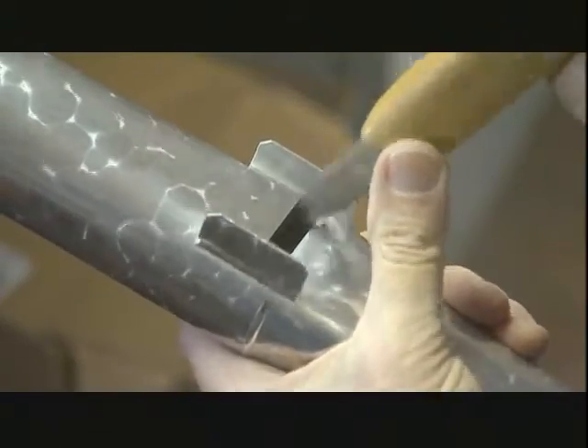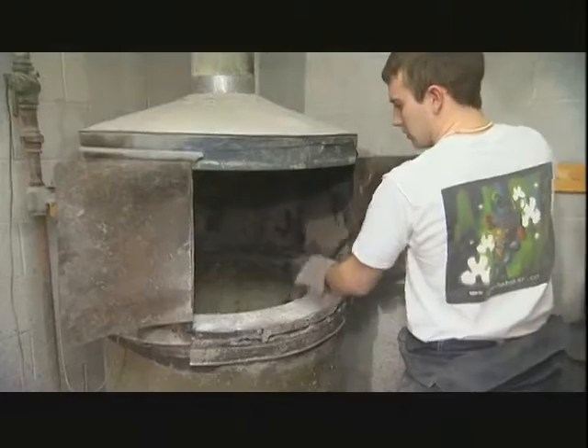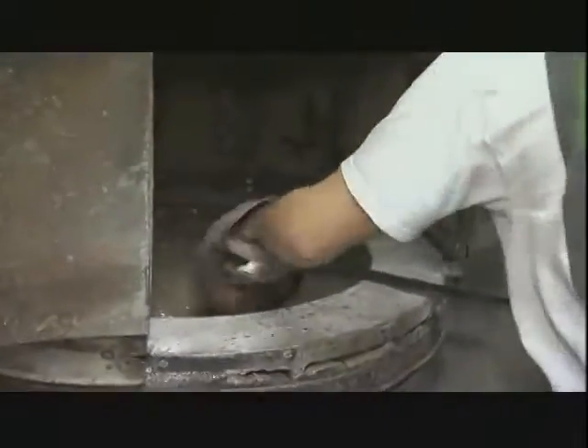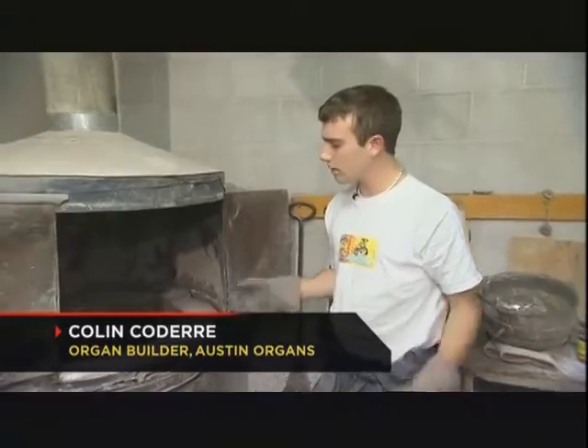The craftsmen have been using lead to make beautiful music since 1893. In the company furnace, lead and tin ingots melt at 750 degrees and mix together within minutes. Removing impurities is simply a matter of adding a little wax, which ignites a fiery process called fluxing. Wax reacts with the metal and brings all the impurities left in the metal to the top.